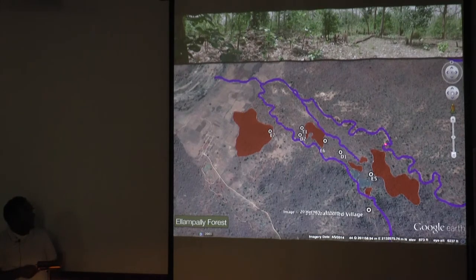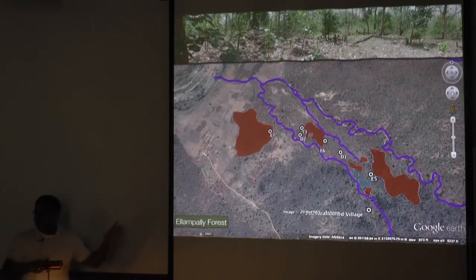And I have a hunch that for each of these smelting sites, a series of slag heaps were created, divided by time. When they came back and resmelted, they put the slag somewhere else. And when they came back again after 10, 15 years, they would put the slag somewhere else, but very close in the landscape.